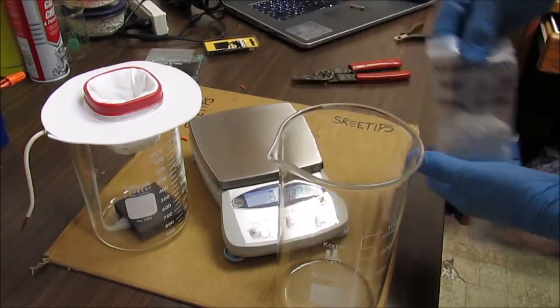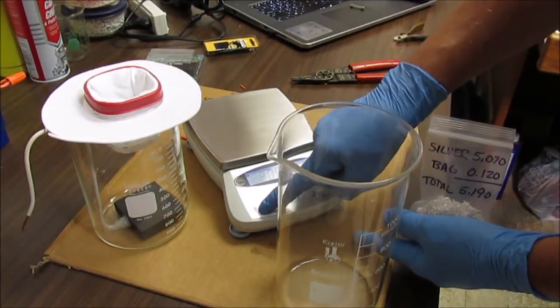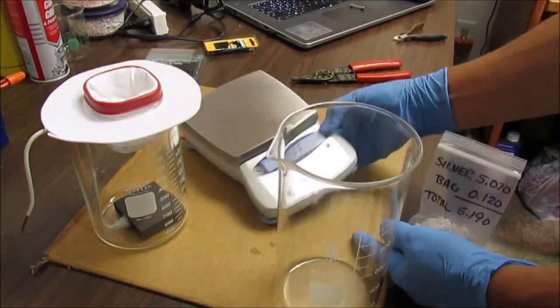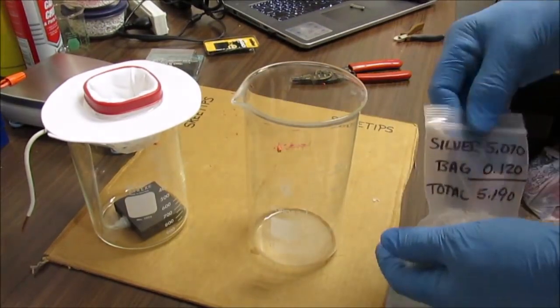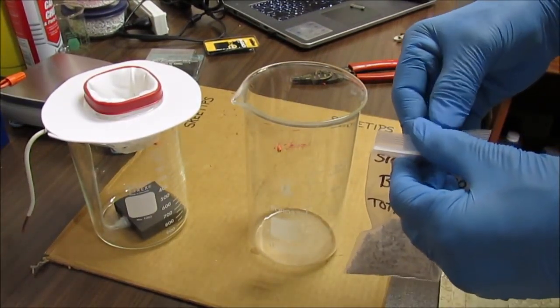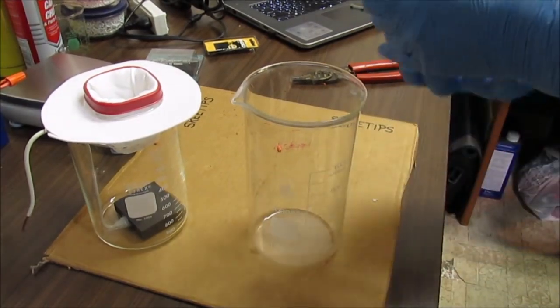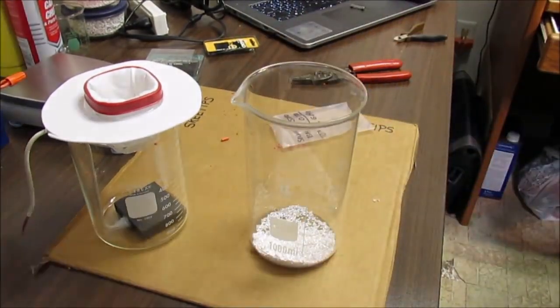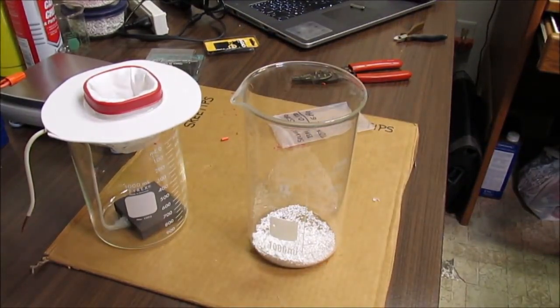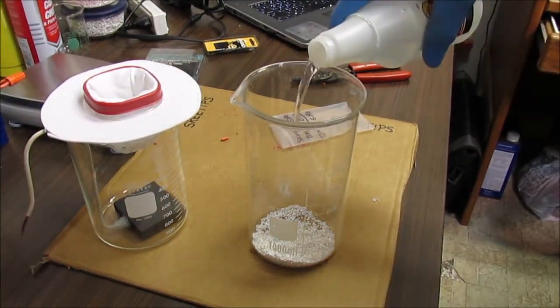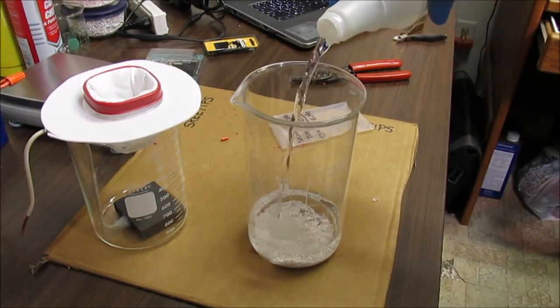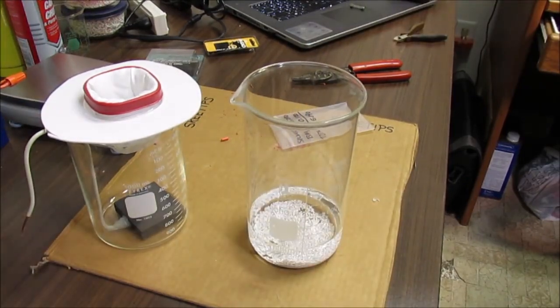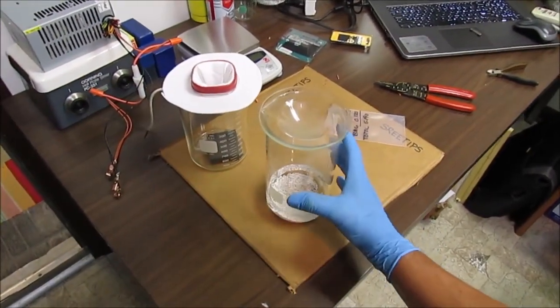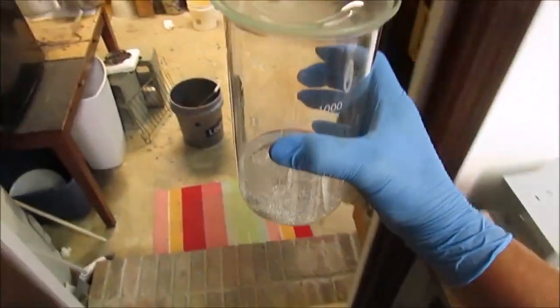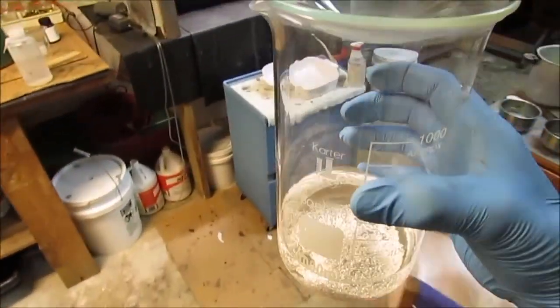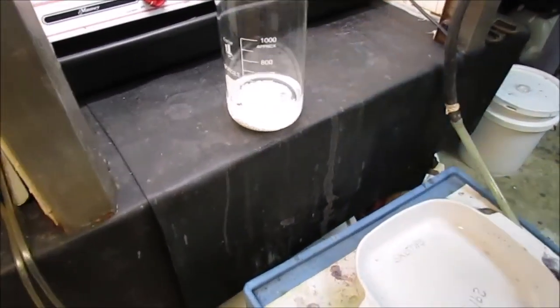Okay, to make the electrolyte, let's get this out of the way. Pour the silver crystal into this tall form beaker. Then we're going to add some distilled water till about the 250, 300 ml level. That's 250 right there. That should be good. Okay, I've got the 5 troy ounces of silver in a beaker here, I've added about 250 ml of distilled water. Now I'll go ahead and put this on the heat.